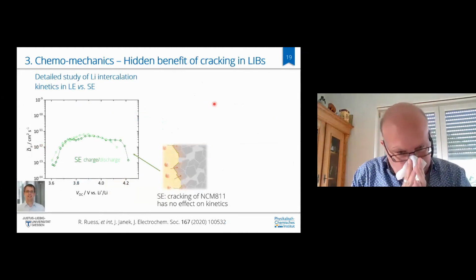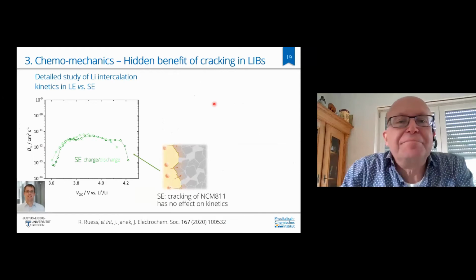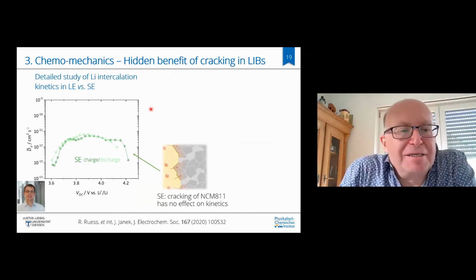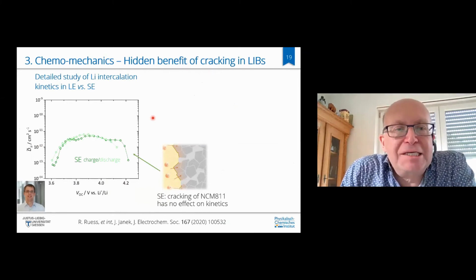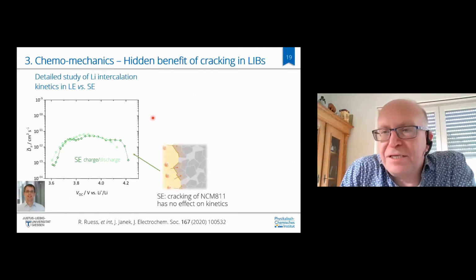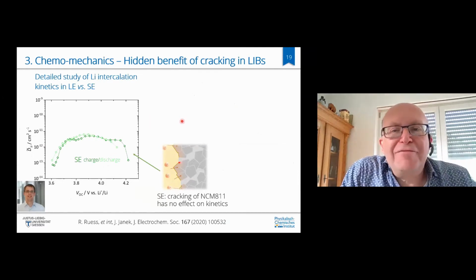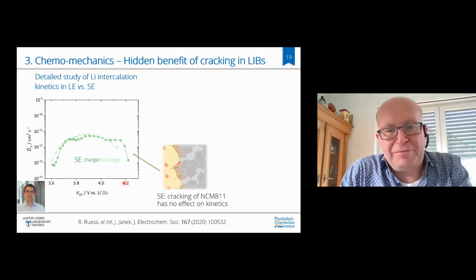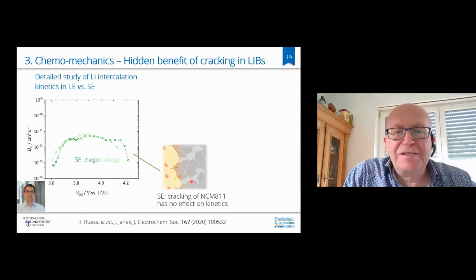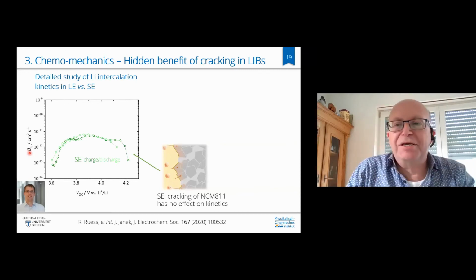Now, something which I think is really nice is something Raphael showed together with Volkswagen recently, and that is a comparative study of the effects of chemomechanical expansion of solid state batteries and liquid based batteries. Let's start with the solid state battery. What you see here is a cartoon of a secondary particle and the solid electrolyte. Now, if we cycle that, you see here the apparent chemical diffusion coefficient of lithium, which we measured in GITT measurements.